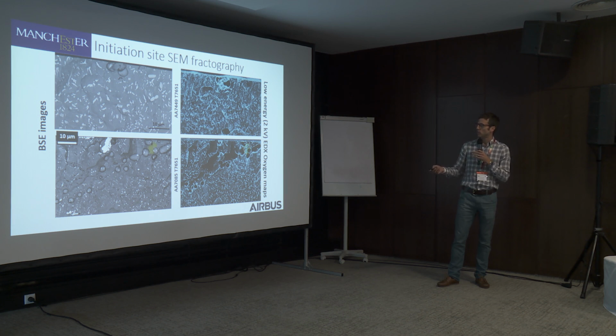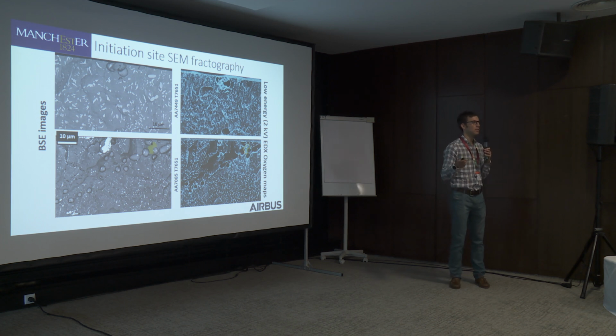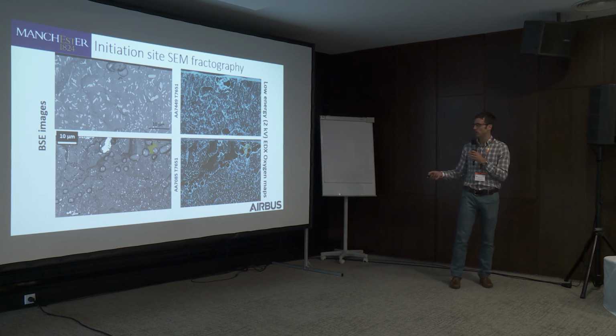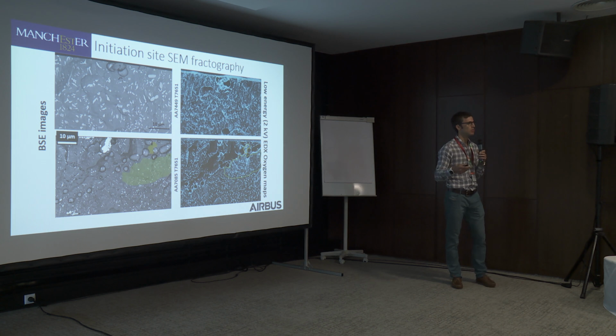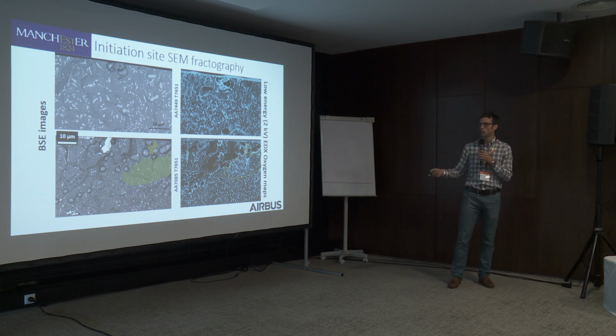So just to highlight these regions, as I've illustrated here in the 7085 sample, we've got a region of elevated oxidation, which is almost the exact point of initiation in the material, between this cluster of pores, creating a very highly stressed, localized region for initiation. And then we've got this region extending up to about 50 microns in total, depending on the different initiation sites, where we have these crack arrest markings across the surface.